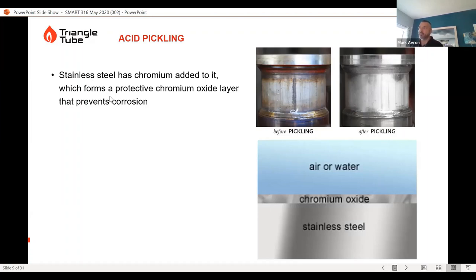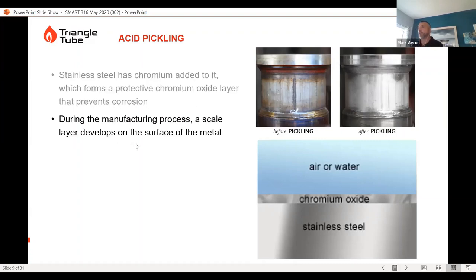We talked about stainless steel having chromium added to it. That chromium naturally forms a protective layer against the stainless steel. If you see the picture on the right here, this middle chromium layer occurs naturally through the manufacturing process, at the molten level of producing the product. But then we start to talk about welding the product. Once you weld the surface, you're going to break down that chromium layer and leave deposits, and a scale oxide layer on the material itself. So the idea of pickling is to restore that chromium oxide layer back to its natural state.